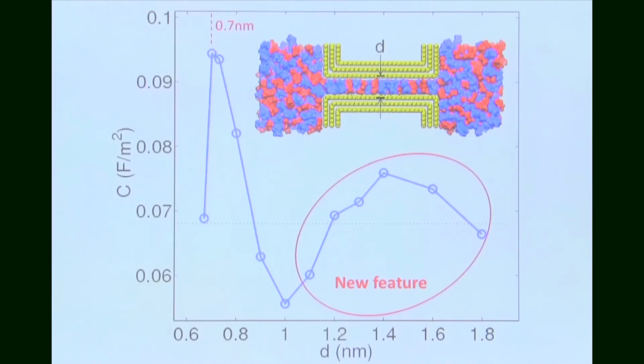This double-peaked capacitance-pore size curve not only shows a good agreement with experimental results for the first peak, but also invites more experimental work to explore the new feature of the second peak. It also provides a possible explanation for the absence of capacitance increase at micropores in some experiments. Clearly, porous carbons could enhance the energy density of supercapacitors.